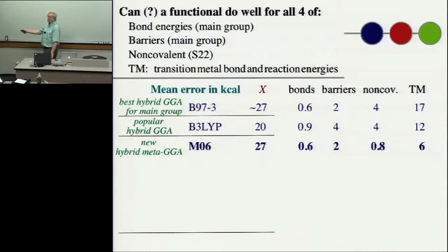There are a lot of hydrogen-bonded systems in there, and pi-stacked systems, which have to do with adsorption on a pi system like an aromatic system. So that's one of the areas where pretty much nobody else has density functionals that work for these non-covalent interactions. But we do. People sometimes call these dispersion-like interactions, but in addition, of course, the hydrogen bond has a large electrostatic and partial covalent character. So we're able to treat a broad range of interactions. We can treat charge transfer, which a lot of density functionals have a problem with too, but we can treat charge transfer complexes. So that's actually one of our successes.